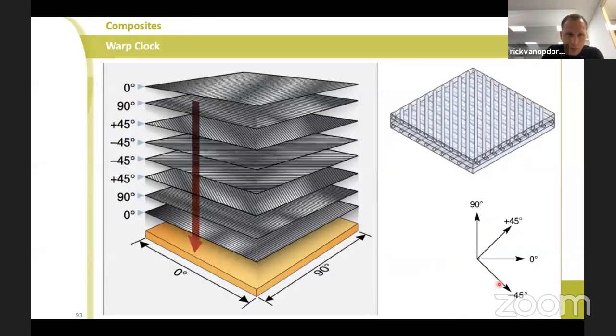Now, I go a little bit further. Now there you see the 0 degrees, 90 degrees, you see the pattern, the stripes, you see all the different angles. And if I make a line here, you see minus, minus, plus, plus, 90, 90. They call this a balanced laminate. And what you see, it's nicely balanced. And once you balance a laminate, it'd be always straight.